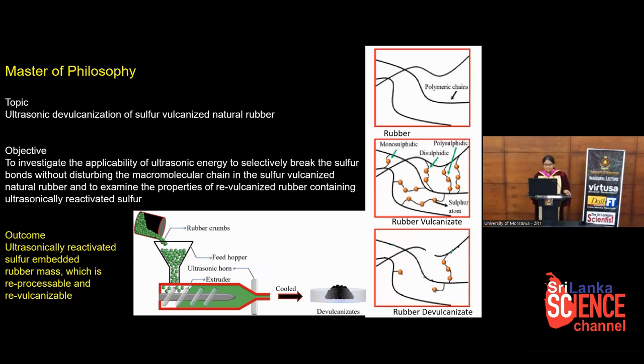Then I started a Master of Philosophy degree, and that is again on rubber-based research. The topic was the ultrasonic devulcanization of sulfur vulcanized natural rubber. Under this research, high energy ultrasound is used to selectively break the bonds, specifically carbon sulfur and sulfur sulfur bonds in the sulfidic linkages, without disturbing the carbon carbon bonds in the main macromolecule. And the outcome was a reprocessable rubber mass, and during sonication, the sulfur that is utilized in the crosslinks is released to the rubber mass, and that sulfur was enough to re-vulcanize the same rubber mass without adding additional vulcanizing materials.